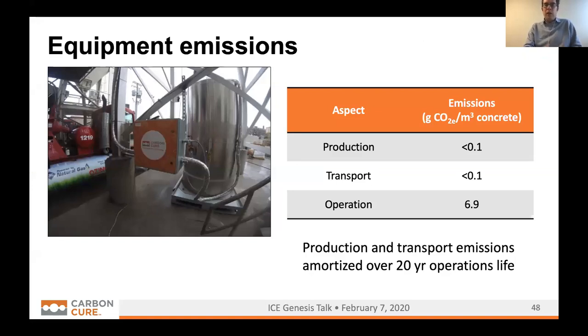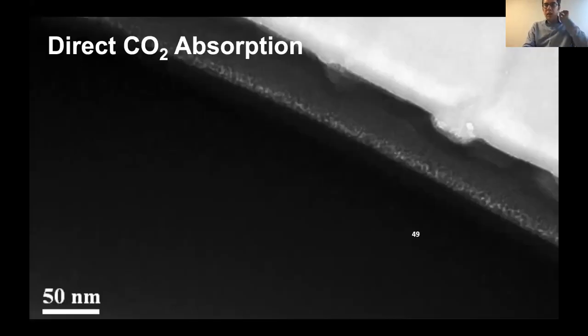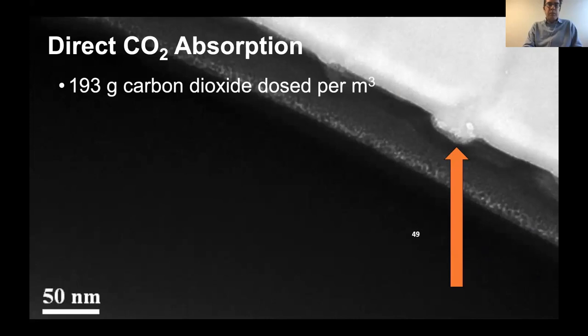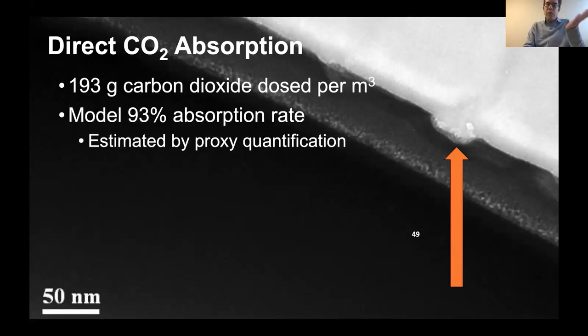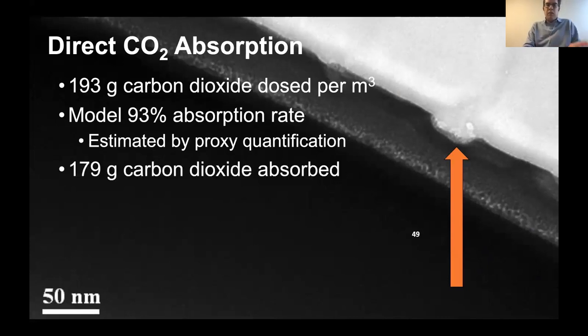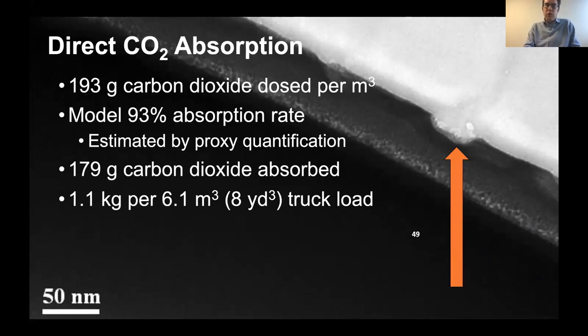The equipment itself, you can talk about the emissions to create it, but then you say this equipment's going to operate over 20 years, and you talk about the amount of concrete that you're going to make over 20 years, then the emissions from the production and transport of the equipment are essentially very, very small per unit of concrete that's produced. Operationally, to run the equipment, say there's electrical energy, that will come up with CO2 emissions that are sensitive to the carbon impact of the electrical grid. With the direct CO2 absorption, for this dose of concrete, we can model that about 93% of it is directly converted. So that's 179 grams. So if you look at an entire truckload, this producer ships about 8 yards of concrete each truckload. So it's about 1.1 kilograms total of CO2 that's injected.